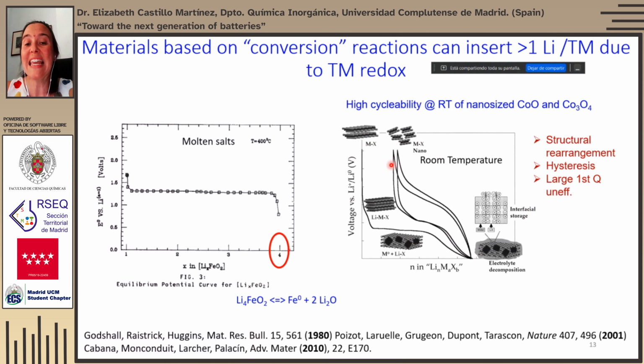And this is because actually the structure that is cycled in the first cycle is different from that of the following cycles. Indeed, during the first discharge, what is proposed is that metal nanoparticles are formed within a matrix of the oxide or nitride or sulfide of lithium, and with also some phases from the electrolyte decomposition.